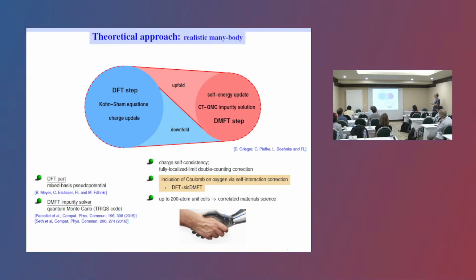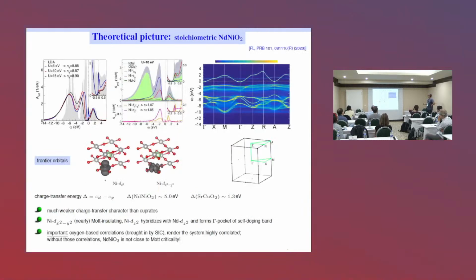It works very nicely because it also gives some band narrowing to the oxygens, and it shifts the oxygens. I think that is important because the system is a late transition metal oxide, it's not Mott-Hubbard-like, and we have to include this. This is the main difference, and the main difference in the results will come from that. So let us look at it; we use a value of U equal to 10.